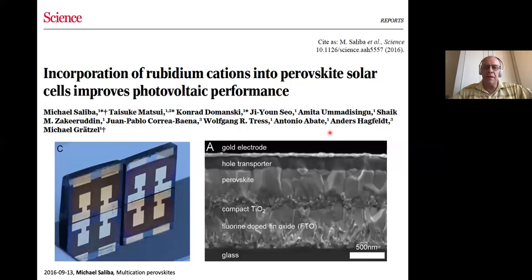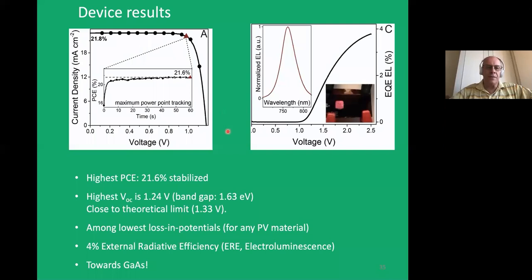So the result we got with this quadruple one was 21.6%. More important perhaps was that the photovoltage was very high. It's 1.24 compared to the band gap 1.63, which means that the theoretical maximum thermodynamically we can get is 1.33 volts. So you see we only lose 90 millivolts from the potential here. And that's really very high. That puts perovskites at the same level as silicon and approaching gallium arsenide.